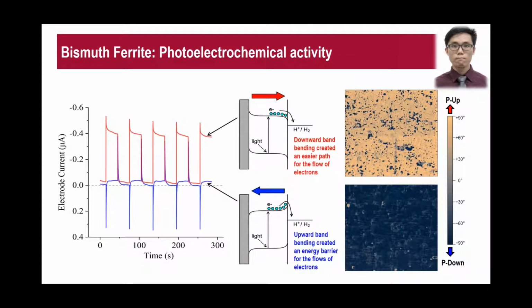And the second one is that we try to understand how polarization can actually affect the response in terms of the PEC activity by having a P up. So you can see on your very right, this figure is indicating P up, polarization up, because we applied an electric field and we measured under the PFM. It shows a polarization upward, in which the sample area, which is 5 by 5, shows the majority having a P up orientation, whereas the bottom is P down, polarization down, all right?